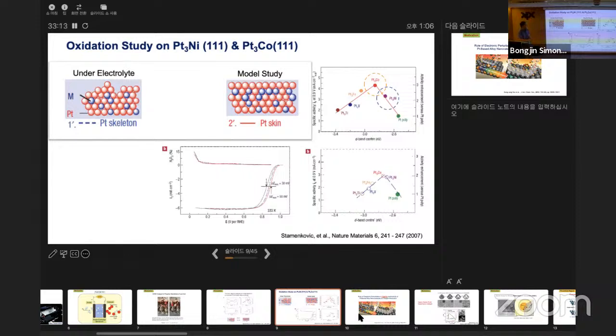But somehow along this way, because I'm preparing the manuscript, we're trying to figure out how to present our approach. To me, this oxide that comes up to the surface probably melted away with the reactions, and the surface became roughened like this. But this surface is somehow more stable than platinum-3 nickel, and that one we are trying to understand: how really this transition metal underneath is behaving. But that's really too difficult.